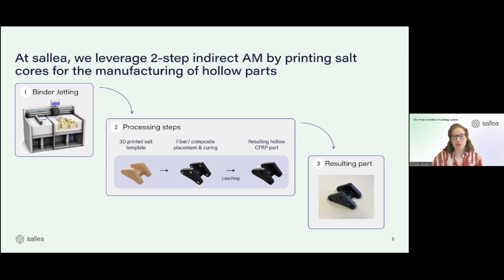For the ones that are not so familiar with additive manufacturing, it's a process where you have a powder bed. And this, in our case, is salt. And then basically you drop the binder onto the powder, and then you build your part layer by layer. And we do this to print our salt cores.